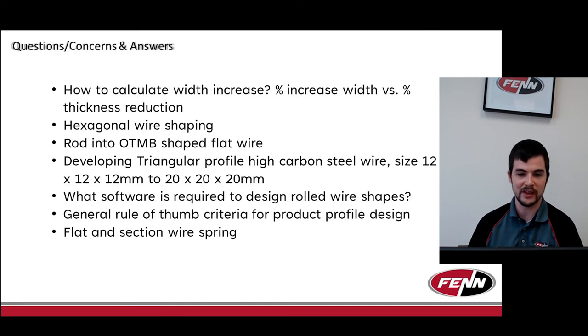A rule of thumb I typically give as a starting point of reference is, using roughly a standard size roll with standard size material, if you want a certain width and thickness as a finish, it's usually roughly the summation of those times about 0.55. That gives you, usually within plus or minus 5 to 10%, your starting diameter that you need to produce that width and thickness. Beyond that, as a very rough standpoint, your roll diameter has a factor on your width.